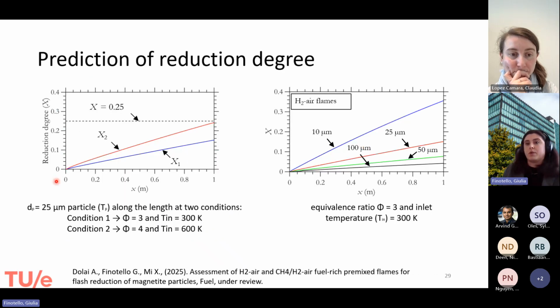So this is a model that can be used, for example, to predict what will be the reduction degree of a particle at the end of the drop tube reactor. But it can also help in designing a new reactor. It can tell us, for example, what length you need for a specific particle to be reduced to a certain reduction degree. And of course, as you can already imagine, if you decrease the size of the particle, you can reach a larger reduction degree within 1 meter of the reactor, at least for this graph.